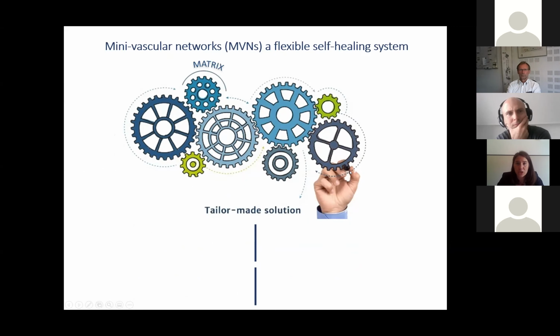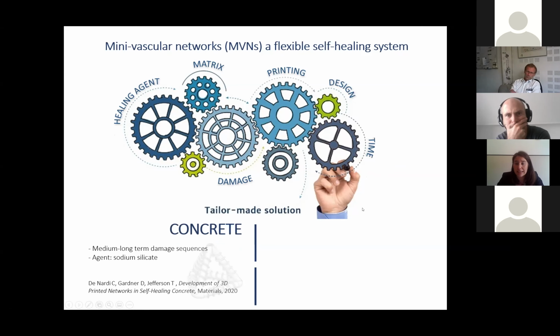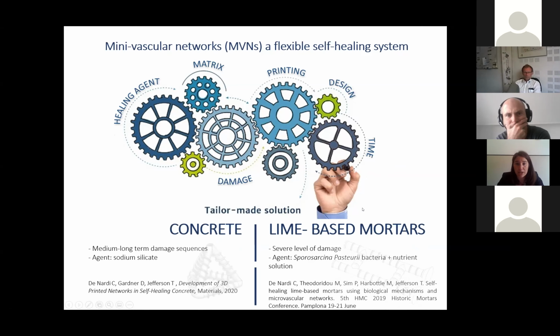Well, the mini-vascular network is a flexible self-healing system, and it's flexible because the behavior is strongly dependent on the matrix properties, on the level of the damage and the time of the damage, on the healing agent properties, on the design of the mini-vascular networks, and on the 3D printed variables. So at the moment, we have studied two different systems for concrete and for lime-based mortars. When the matrix is made of concrete, we have studied medium and long-term damage sequences, and we used sodium silicate as healing agent.